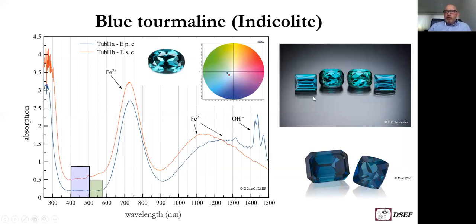And in Namibia, you also find stones which are blue, greenish blue, or indeed pure blue, as you can see in these stones here. And here is a corresponding absorption spectrum, again polarized, and you can actually see here that the manganese titanium or iron titanium band is lacking, leaving behind the transmission maximum here in the blue area, and this is why the stone is blue. And you can see here the corresponding points in the color circle, which plot in the blue area. And these blue tourmalines actually are known under the name indicolite. Now, one may ask why this is maybe derived from the indigo blue. Why is it not written with the G? It is actually not derived from indigo, it is derived from the term indicum, which is a Latin term for a plant.